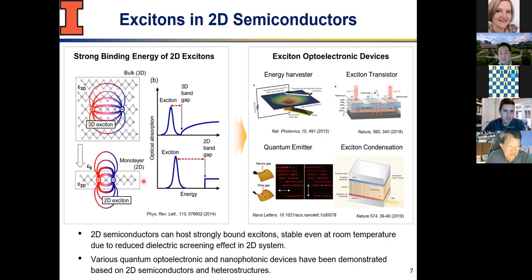So there's no need for this phonon to get involved. So that's good for optoelectronic applications. What's actually really interesting for 2D is not that it's only thin, but when it becomes thin, if you think about electrostatics, so I have, let's say, an electron hole pair, I get to create them. In a bulk semiconductor, I have lots of materials on top and bottom, and those materials have a higher dielectric constant than the vacuum or ambient. So if you look at the field line of the bulk versus as simple as one layer, you start to see that the screening by the bulk components substantially shrinks when it comes to single layer. So-called the dielectric screening is gone.